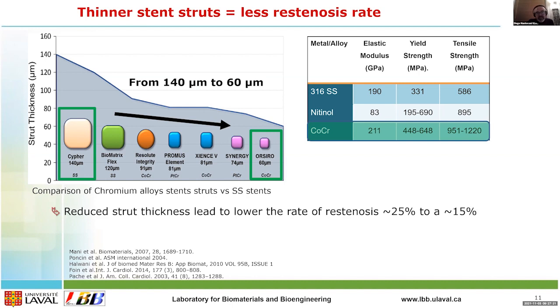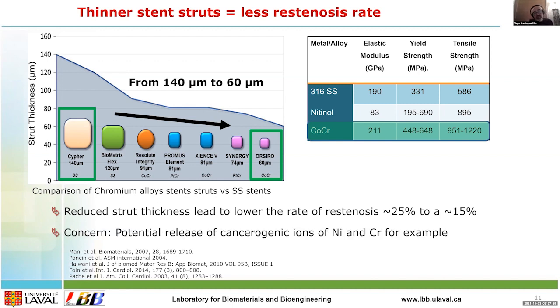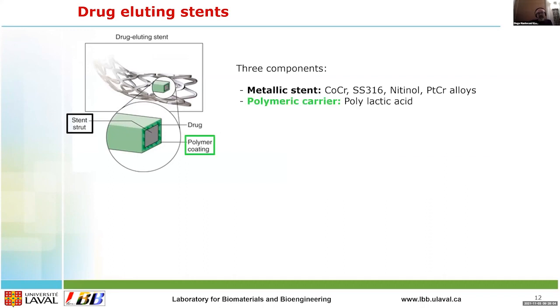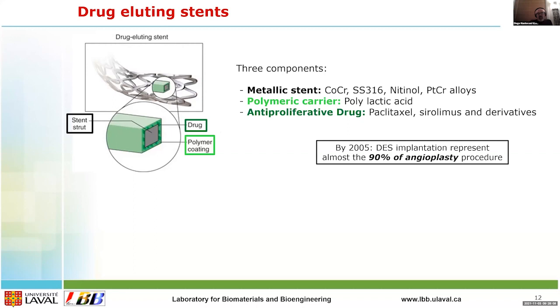Reducing the strut thickness led to lowering the stenosis rate from 25% on average to 15%. But still, we have one stent in 6 that doesn't work. Also consider one point: stainless steel, nitinol, and cobalt chromium contain chrome and nickel, and these are considered allergenic, potentially cancerogenic, certainly cytotoxic, and eventually genotoxic materials. So basically, there is the potential of contamination of a patient. And that's why, starting from 2005, there was the development of drug-eluting stents in the world.